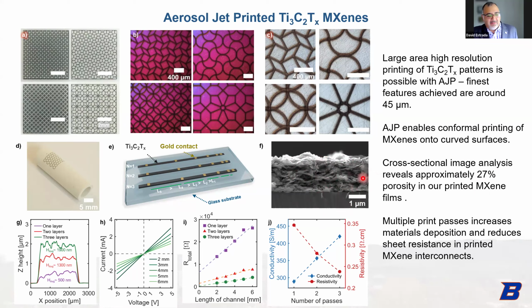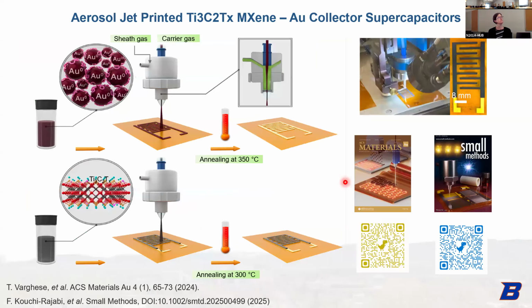Other compaction steps, or something, to try to reduce the porosity. This is a pretty common capacitor. We actually use a gold current collector, and for that, developed our own gold ink. So we use a gold nanoparticle ink. We print our energy storage electrodes. We anneal that at 350 to remove the solvent, and then print over it and use our MXene developed ink.